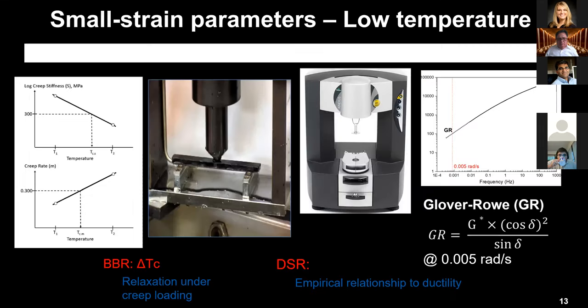Next, I'm going to briefly go through some of the rheological work and give a brief summary of each of the primary tests that were done and how those correlations are going to be used by Illinois. Bending beam, or delta Tc, and dynamic shear Glover-Rowe were the small strain, low temperature parameters evaluated. These tests indicate the binder's low temperature performance. Bending beam is related to relaxation, and Glover-Rowe is related to the ductility. Ductility and creep loading, relaxation, are related to distresses caused by negative temperatures, not loading.